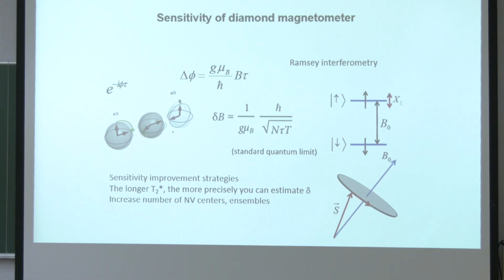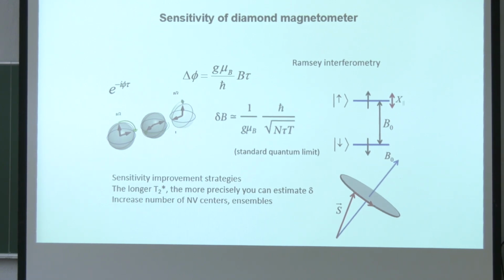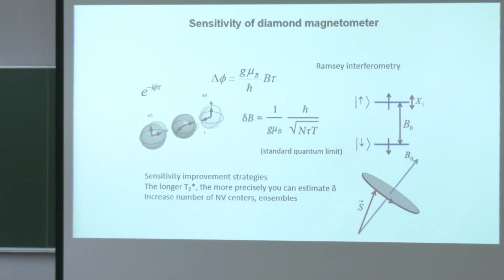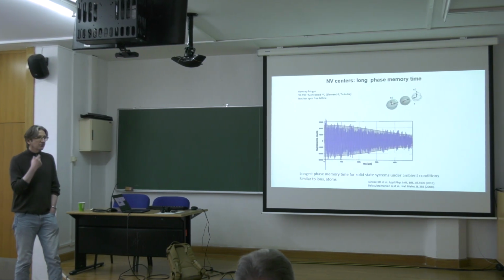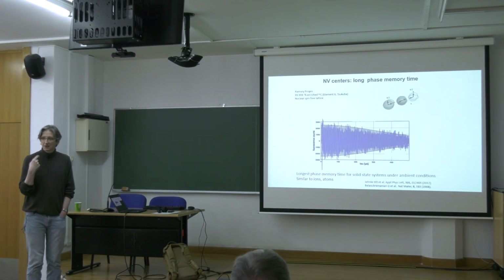So the only parameter that helps you in increasing the sensitivity for a given measurement time is the coherence time. You need to acquire the phase for longer to reduce the noise. That's true for actually any quantum sensor, if it's limited by the projection noise. And for the NV center in diamond, this T2 time is quite long.